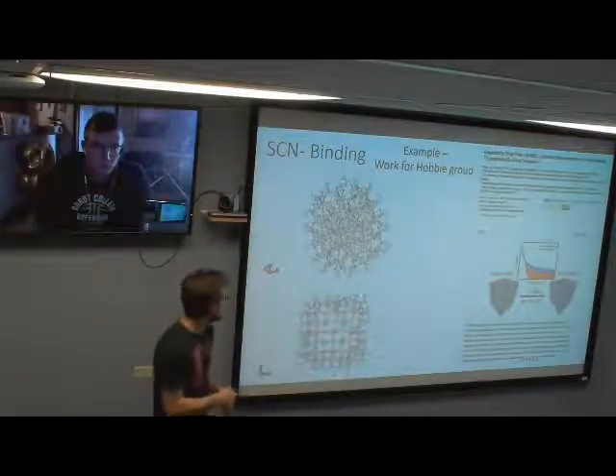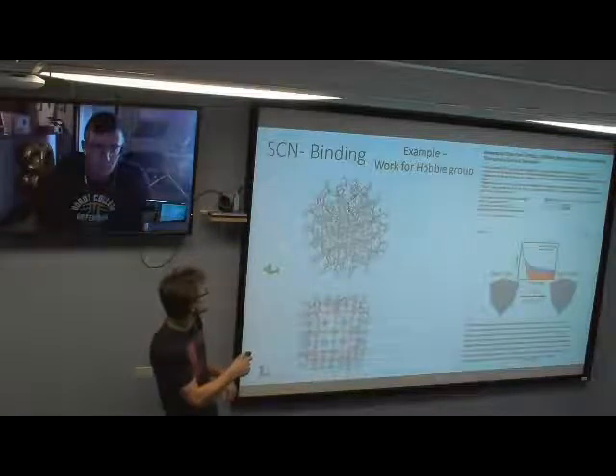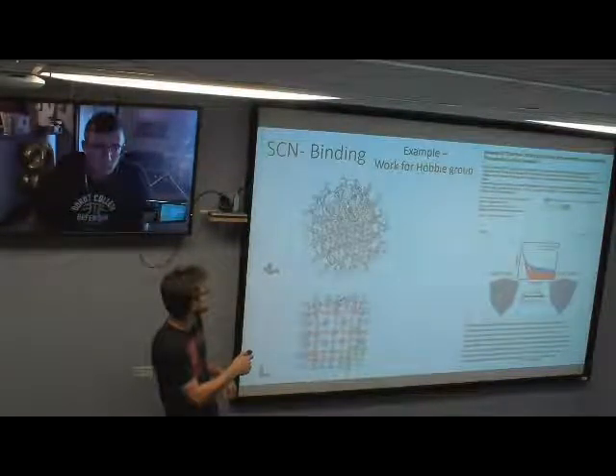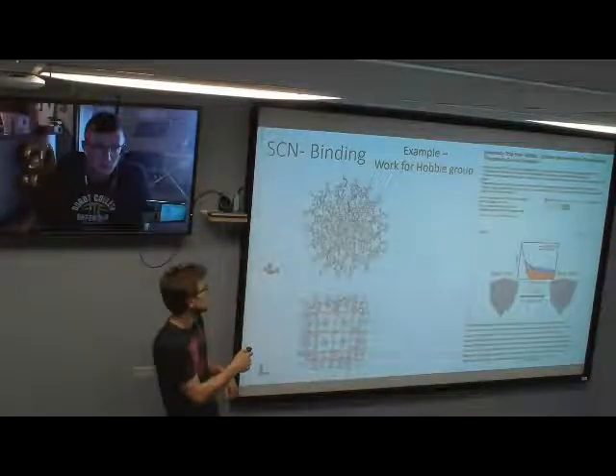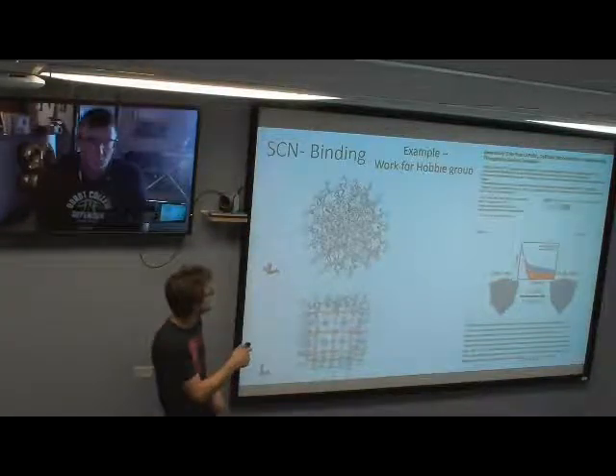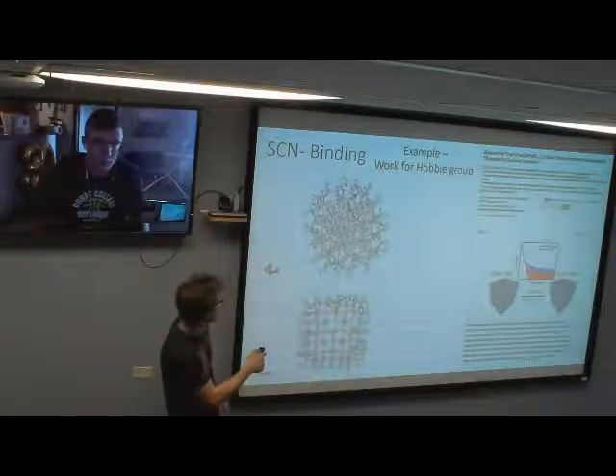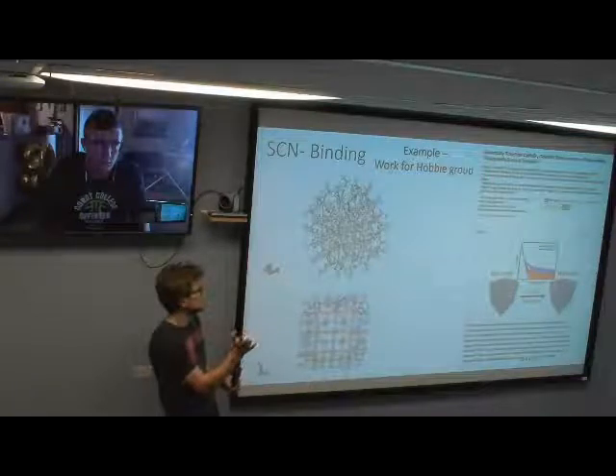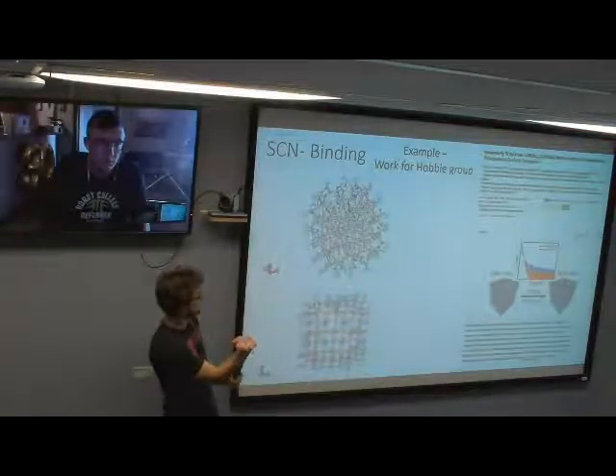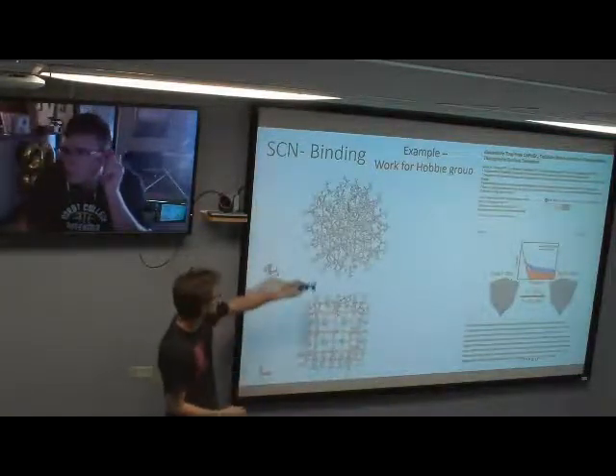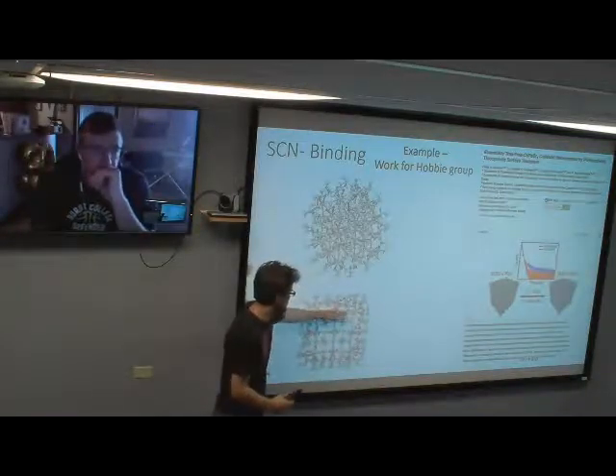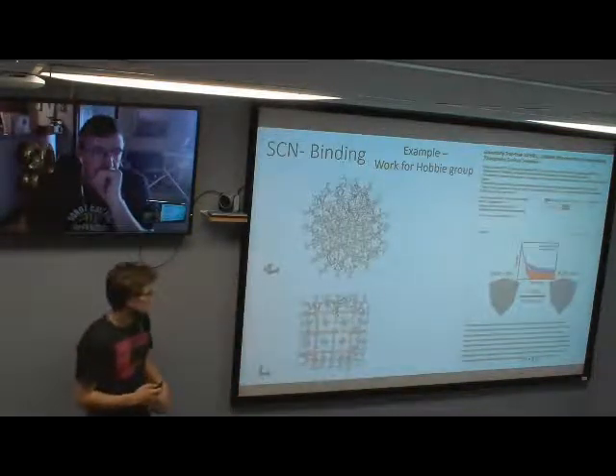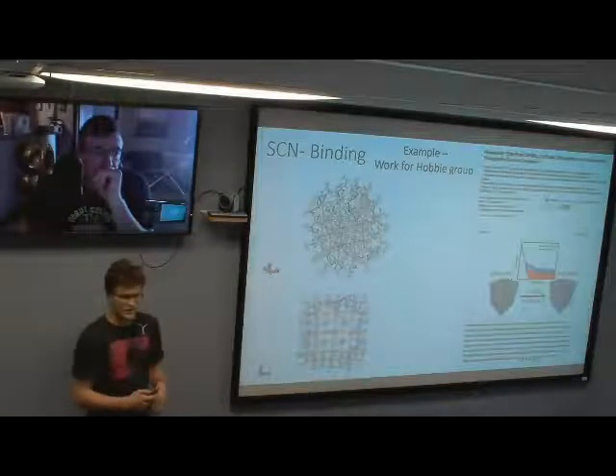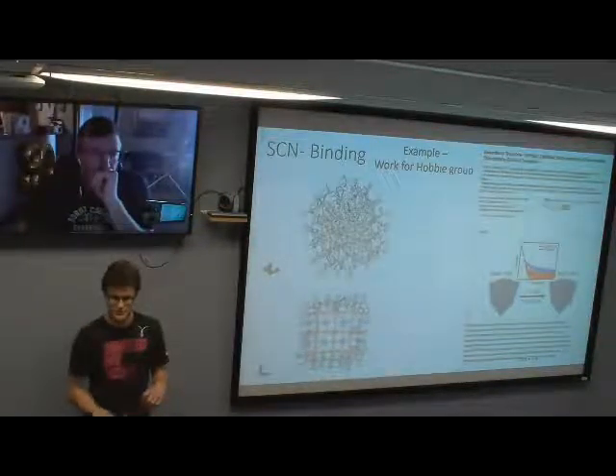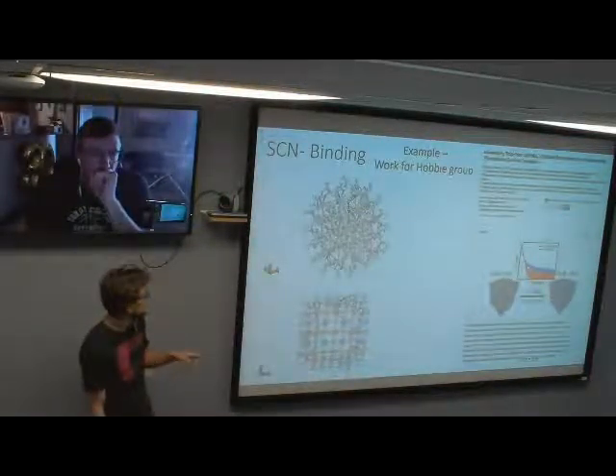And you can see it binds, so the sulfur binds to the positive lead ion because the sulfur has the negative charge on it. And it binds at kind of like 20 degrees. Like if this was your zero, so about 20 degrees. And it seems like it's doing some sort of hydrogen bonding interaction with the ligands, with the amine ligands anyway.